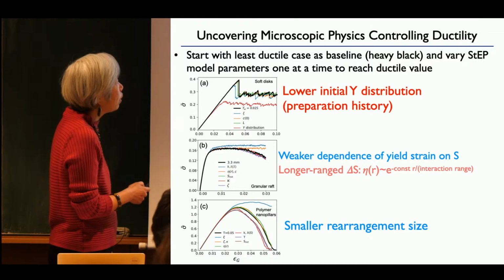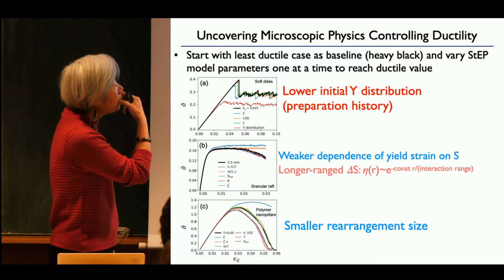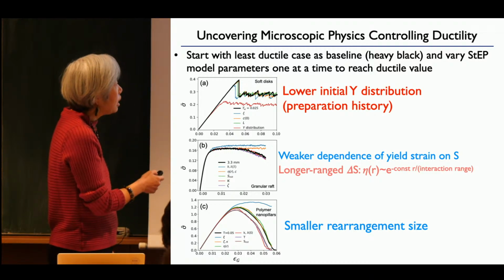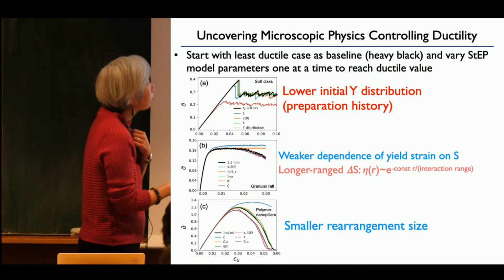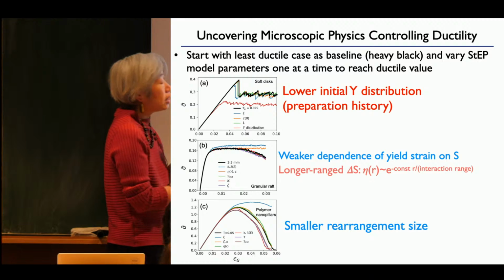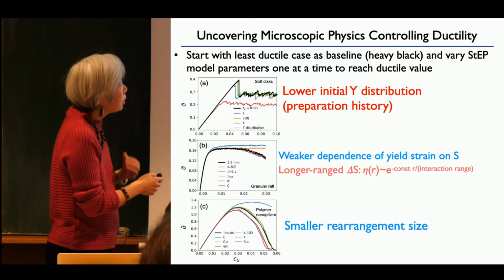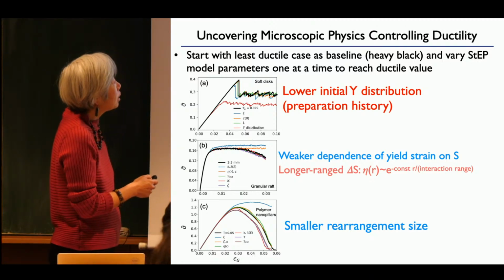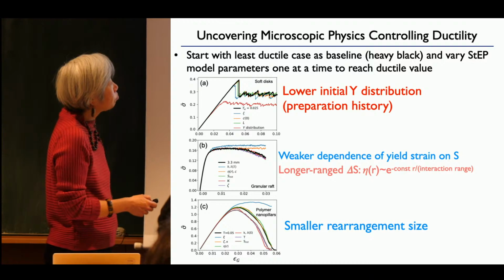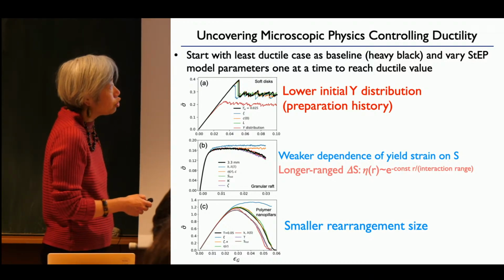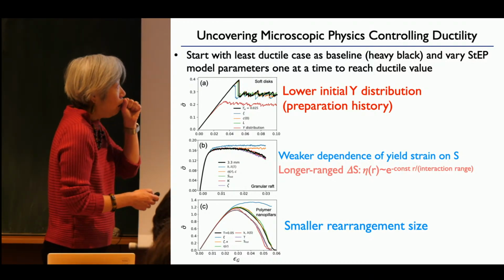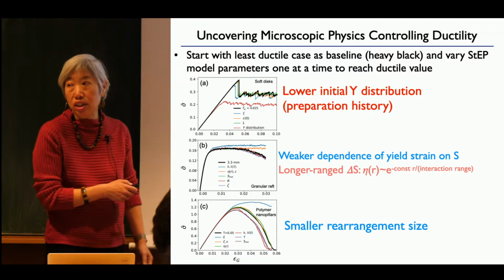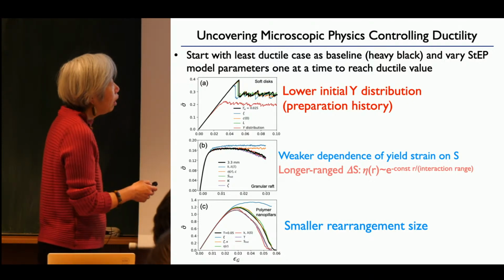So now let's look at the granular system. In the granular system, you see that there are two things that each could make the difference, and so we can't really distinguish between them. But one of them is that the yield strain in the more ductile case has a weaker dependence on the softness.